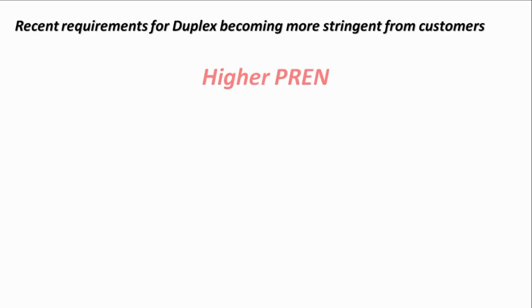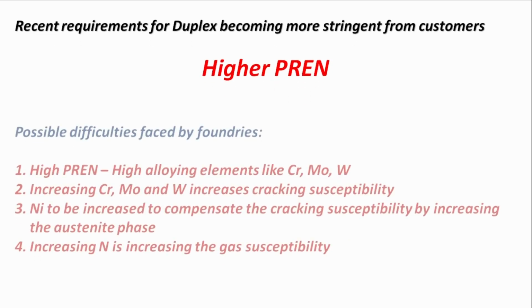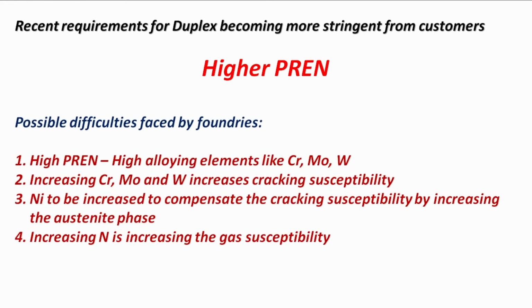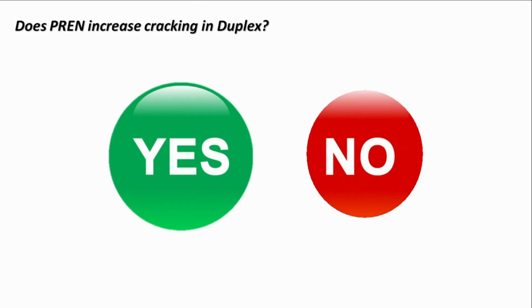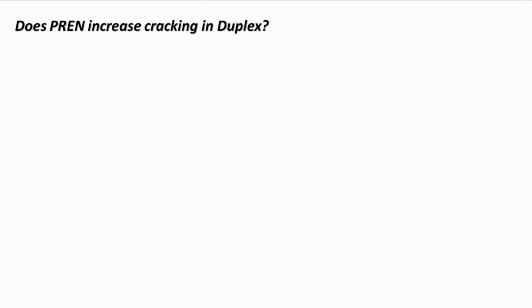Now from customers, we are getting a lot of stringent requirements with higher PREN. The possible difficulty we face is higher PREN, high alloying elements like chrome, moly and tungsten. Chrome, moly and tungsten increase the cracking susceptibility of the material. But really, is PREN a problem? Yes, and sometimes no. So we have to understand when PREN is a problem.